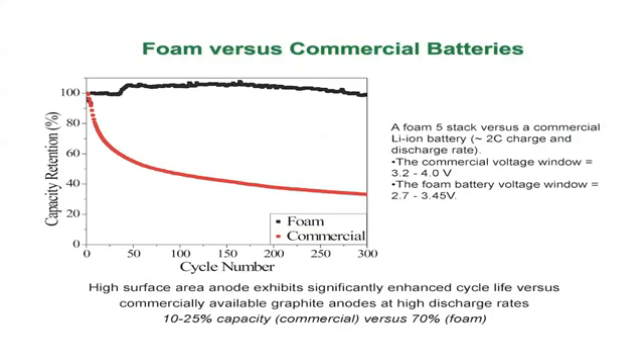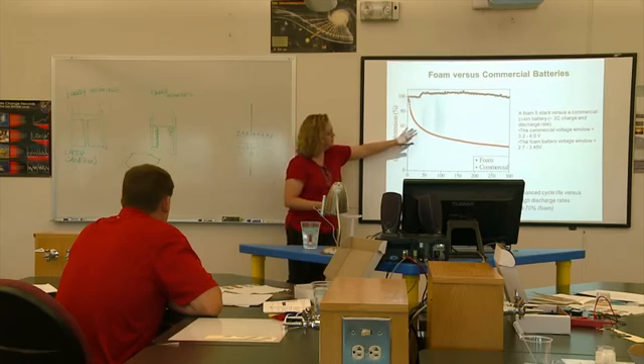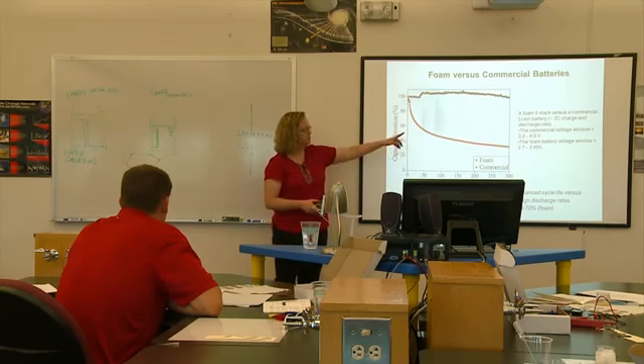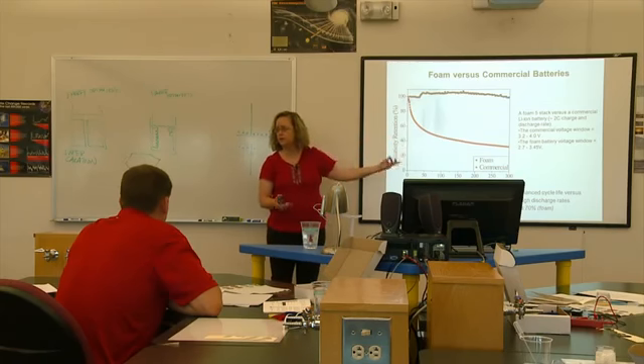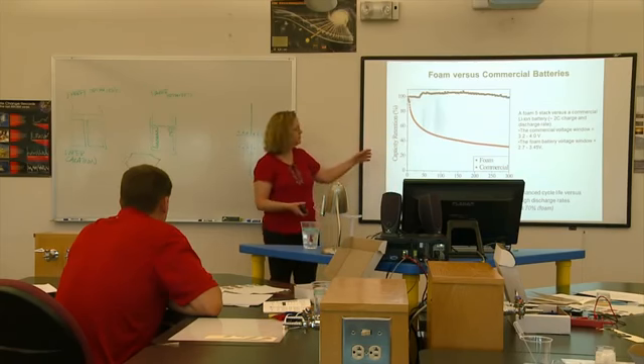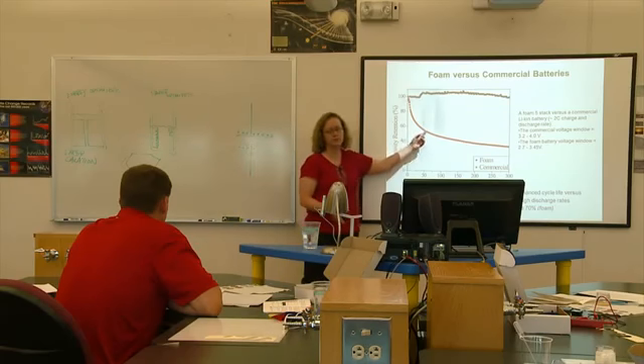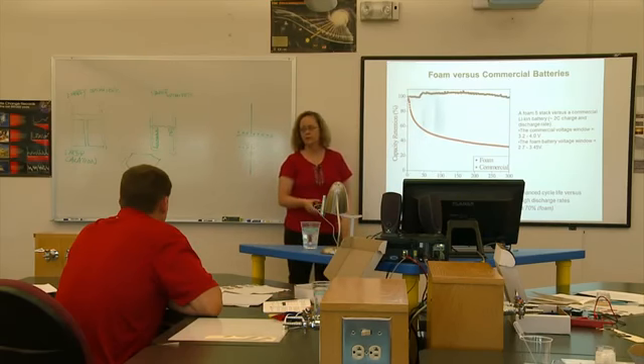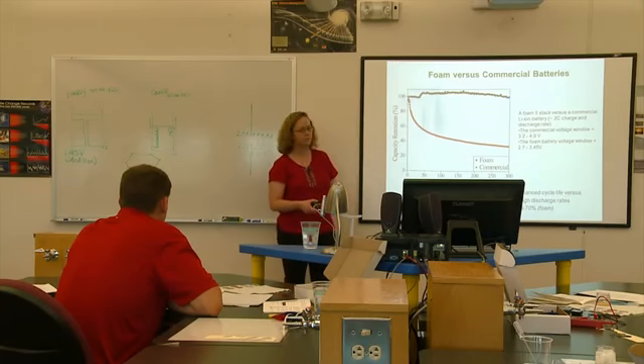So what we did is we took our battery again. Now it's not the full 3D battery, it's just our anode. We took a normal battery out of a BlackBerry actually, stripped its controls off and cycled it the same way. What I'm showing you in black is our battery, and in red is the BlackBerry battery. The voltages were different because the cathode materials were different. But what you can see is that a commercial battery is just not meant to cycle that fast for that many times. So its capacity drops pretty dramatically, whereas ours is still better.